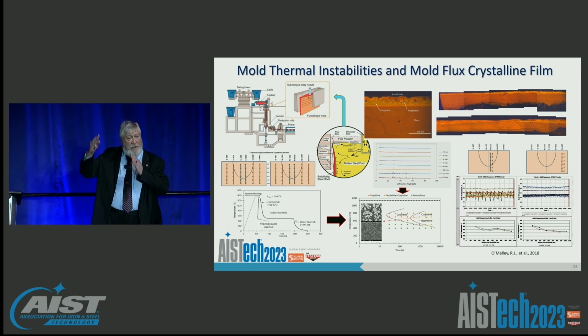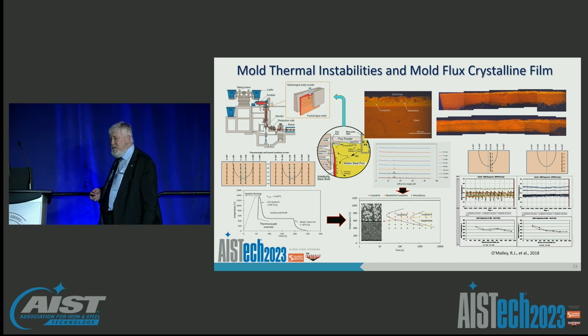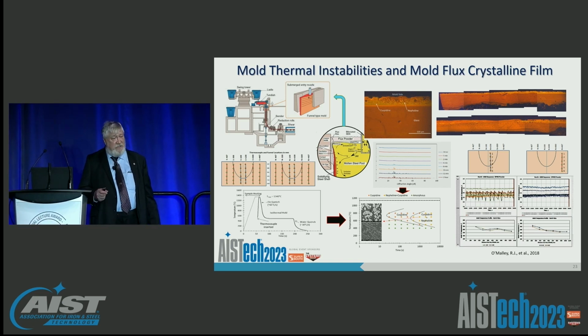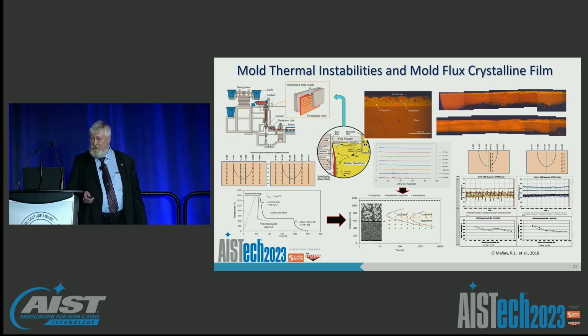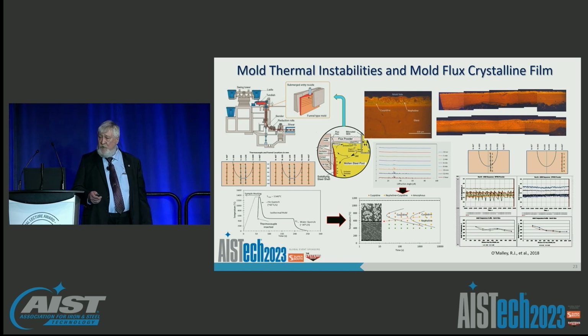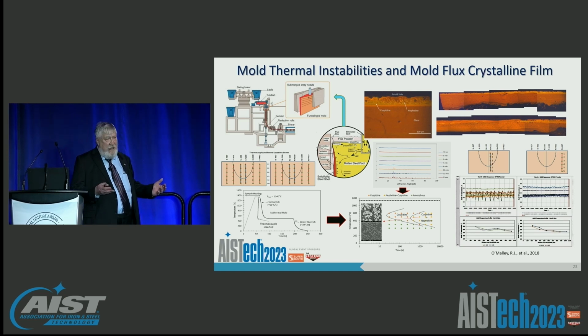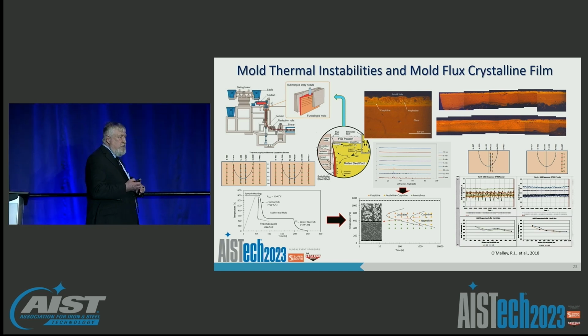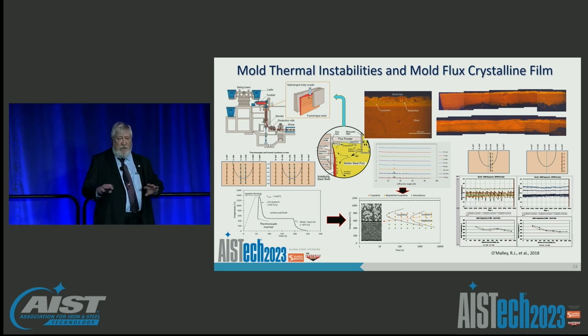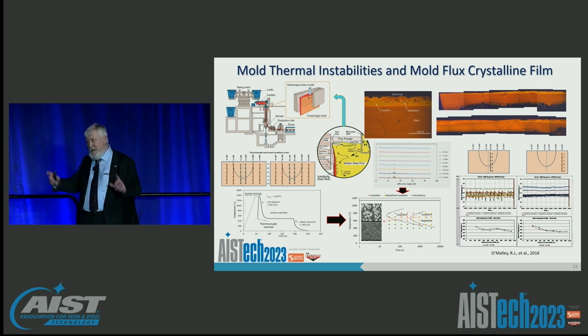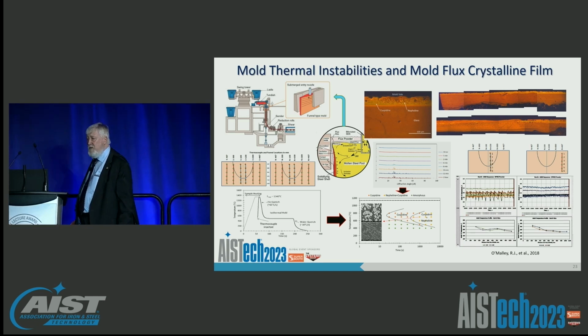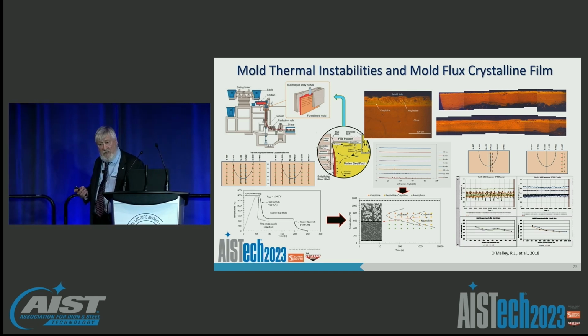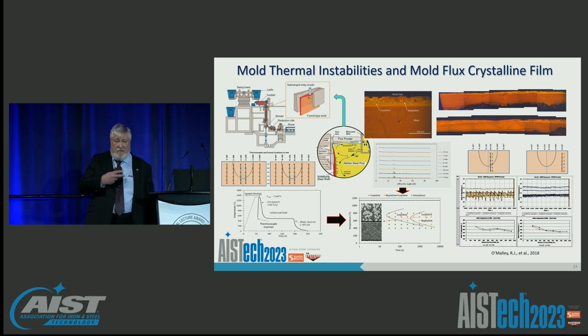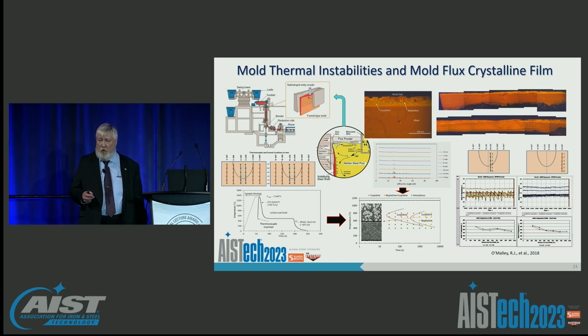And this occurs repeatedly over time. Well, with these types of systems, we were still very lucky to catch this, because even in this densely instrumented mold, we were lucky to catch that type of behavior in the funnel root area. And by the way, with conventional sensors, breakout detection systems, or mold heat removal measurements, you would never see this behavior. It is hidden by the fact that it's in a small area relative to the total heat removal of the process. But it is very disruptive, and it's one of the reasons that sometimes these types of mold designs actually exhibit centerline longitudinal defects.